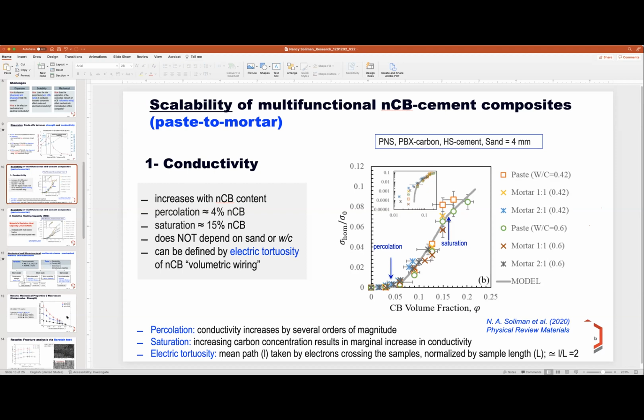So which ratio are you working with at this moment that gives the desirable electrical conductive effect, the Joule effect that can warm up the concrete uniformly? I can say maybe from 8 to 12%, you will have good conductivity, good resistive heating, and also acceptable strength. But beyond 15%, we have a big reduction in the strength. Yeah, that's what I was asking, okay.